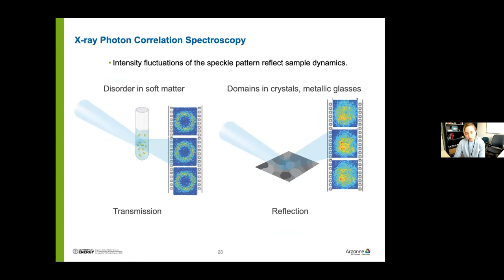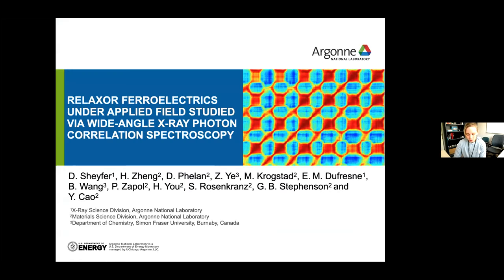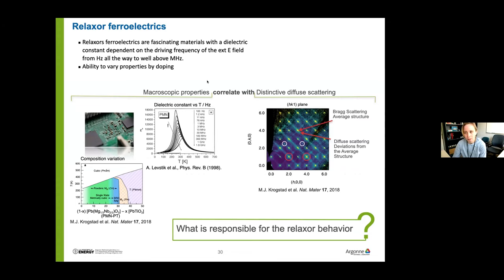I have shown you an example of probing dynamics in disordered soft matter — but can we do XPCS with crystalline matter? Yes we can. We can perform XPCS in reflection-type experiments. I would like to show results from recent work where we probed wide-angle XPCS in situ on relaxor ferroelectrics. Relaxor ferroelectrics are crystalline materials with interesting properties: the dielectric constant depends on the frequency of an external driving field, spanning from hertz to megahertz regimes, and they have a remarkable temperature dependence.